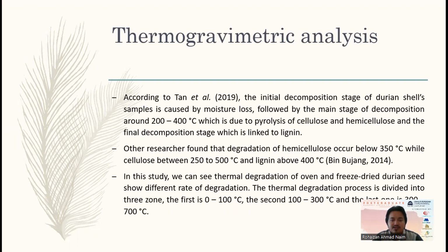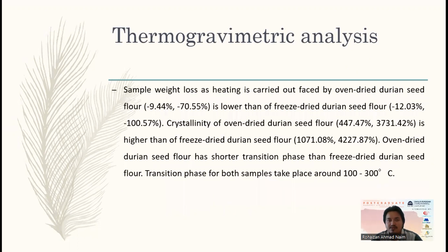In this study, we can see thermal degradation of oven and freeze-dried durian seed shows different rates of degradation, which can be divided into three. The first one is 0 to 100, followed by 100 to 300, and finally 300 to 700 degrees Celsius.